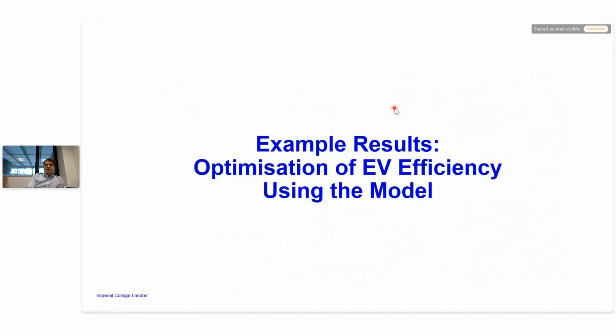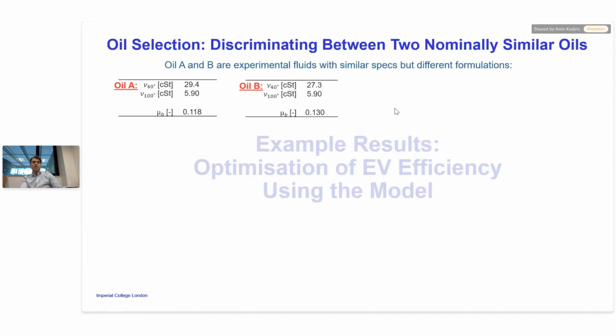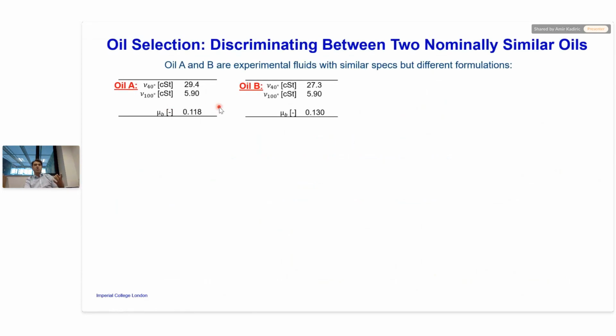Having validated it, we then took that model and tried to analyze the efficiency of the electric drive unit for different oils. So the first thing we did is take two oils, experimental fluids, not real commercial fluids. We call them oil A, oil B. Very similar, so these are the viscosities at 40 and 100 degrees, 29.4 and 5.9 centistokes versus 27.3 and 5.9. So roughly Dexron 6 specs. It's an ATF. I've deleted some of the property fluids here because this is a recorded webinar.